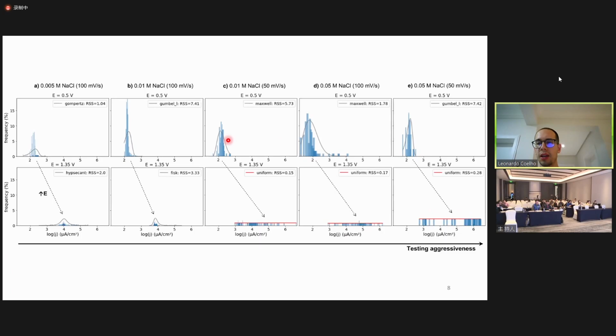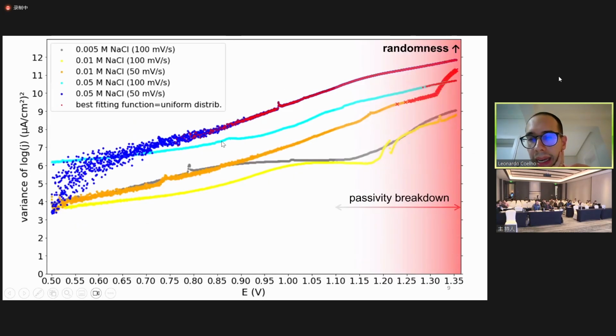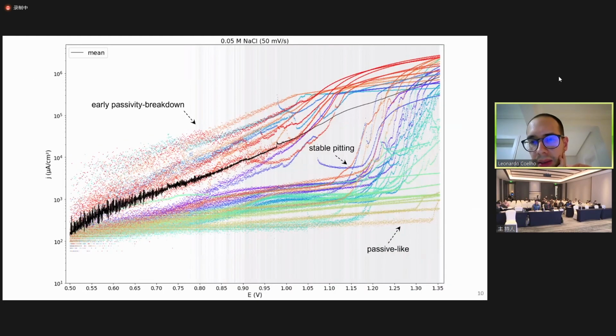And this trend was verified not only for increasing testing aggressiveness, but also as a function of potential. So we realized that, as I mentioned, this higher likelihood of fitting the data with the uniform distribution was directly related to the higher randomness of the current density. So we decided to follow closely the variance of the current density as a metric of randomness in this case, but you could use different types of randomness metrics. And interestingly, this region was completely correlated to the passivity breakdown region, which now appears to us to be a region we should look at more in statistical terms rather than in terms of well-defined regions. And this high randomness is ultimately linked to pitting phenomena or localized corrosion.